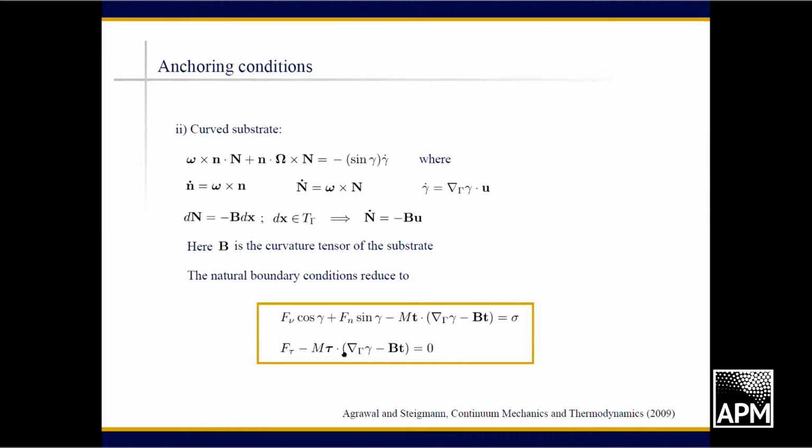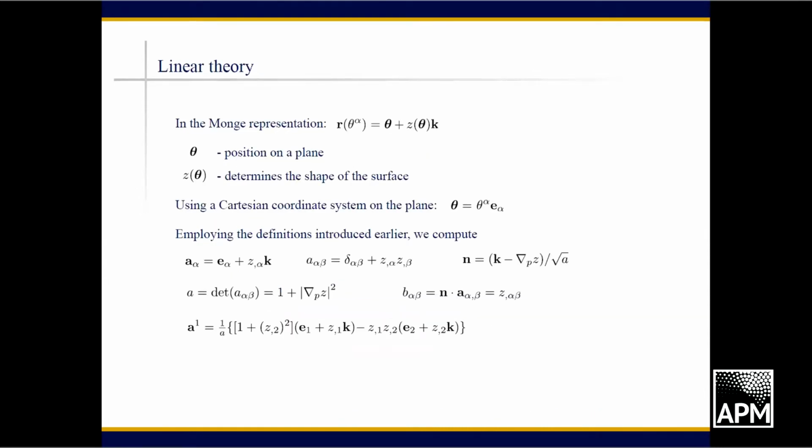And we have also an additional non-standard equation, which arises solely due to flexural stiffness and is therefore absent in the classical capillarity theory. And in the absence of flexural energy, this reduces precisely to the classical Young-Laplace equation involving a surface tension, cosine of the contact angle equals the adhesion energy. And these intervening terms are associated with bending energy of the bilayer.